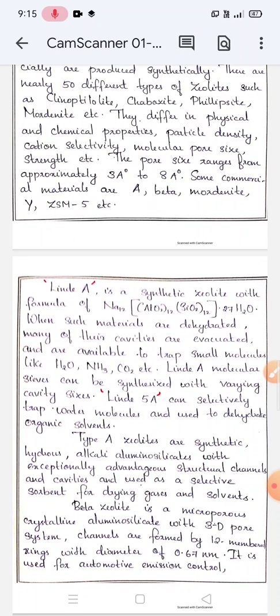Since zeolites differ in molecular pore size, we can also synthesize molecular sieves with varying cavity sizes. Linde 5A is a molecular sieve with a pore size of 5 angstrom and it can selectively trap water molecules and is used to dehydrate organic solvents.